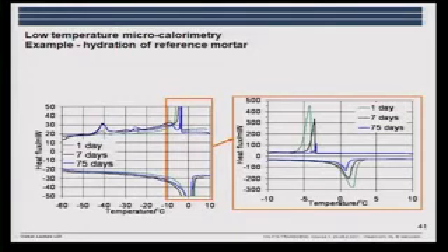And here you see an example of some materials where you have a reference. It's mortars, just an ordinary Portland cement mortar, where you can see the change in freezing curves of samples cured for 1 day, 7 days, and 75 days. And when you look at this, you can see that at 1 day we have very little of the fine pored material, but it's increasing with time, whereas initially we have a lot of water freezing at high temperature, whereas at 75 days nearly none. So we have got finer porosity and maybe many threshold pores.